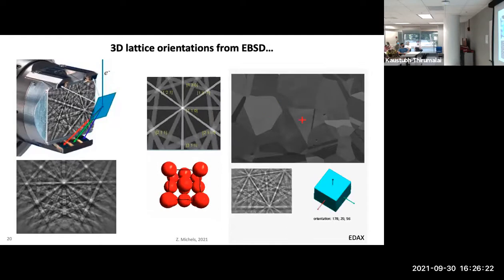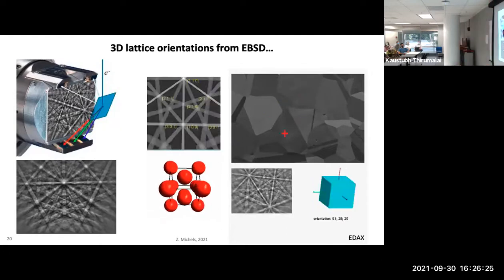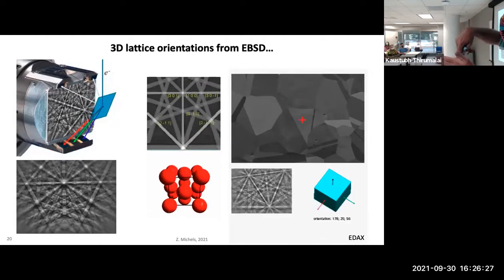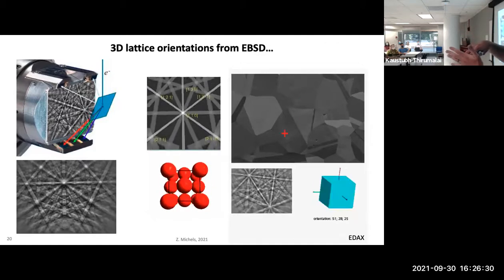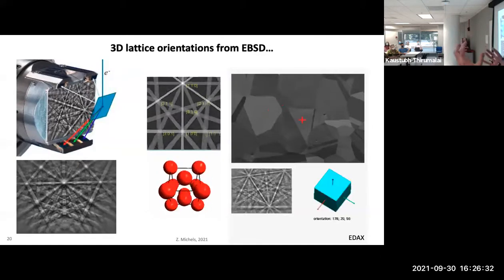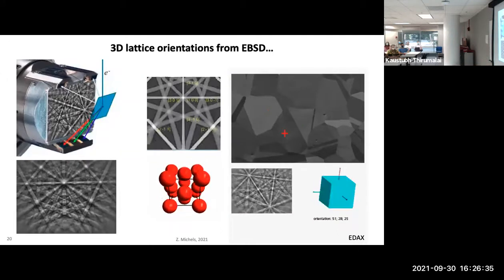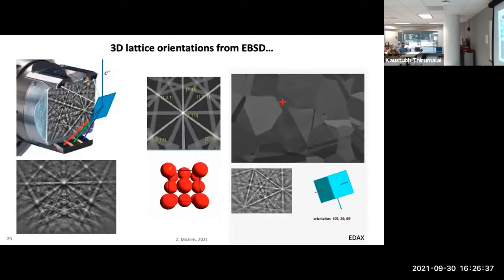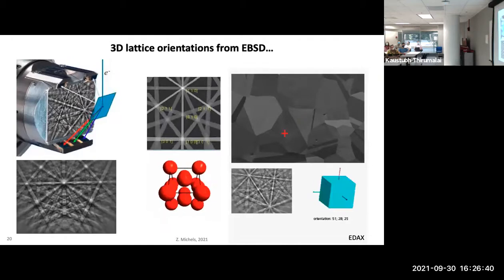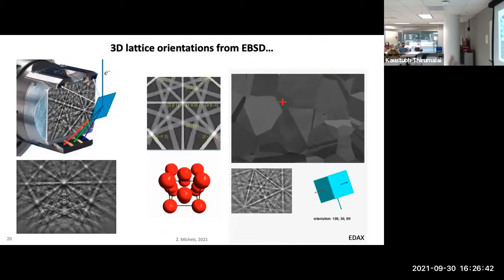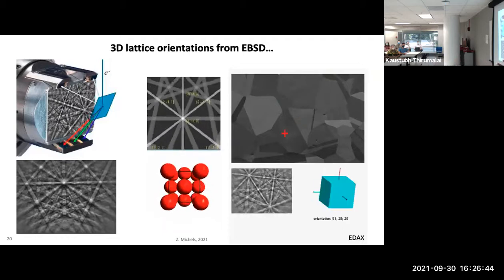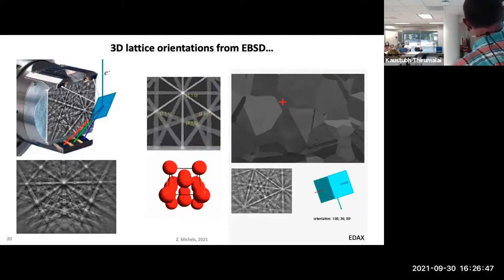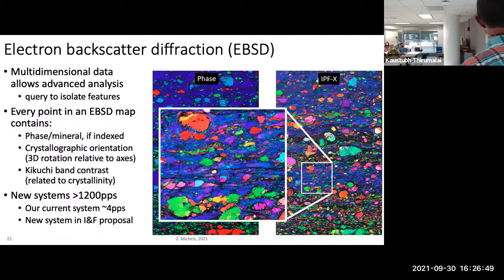And so what we can do with this is map, even though it's a single 2D surface, we're getting a slight amount of 3D interaction with that material. We're able to map the 3D crystallographic orientation. And that is different from doing something like a universal stage where you can only get, say, the optical axis of a mineral. In this case, you're getting all the 3D information about the crystal orientation.